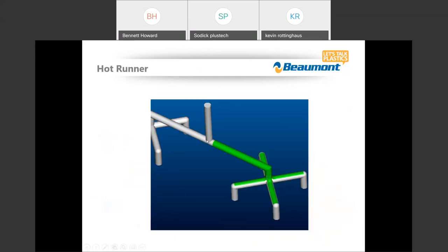So I mentioned in a hot runner doing elevation changes. Sometimes we hear people talk about elevation changes thinking that they're going to solve an imbalance because we're turning the runner system. Again, turning the runner system doesn't alleviate an imbalance. In a hot runner system, our first intersection is actually at the base of our sprue. So we have our annular ring here coming at the nozzle to sprue interface. The annular ring comes up to the first intersection, which is at the base of the sprue to the primary runner system, and those laminates split and they continue on their way.